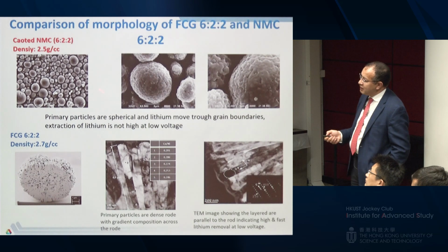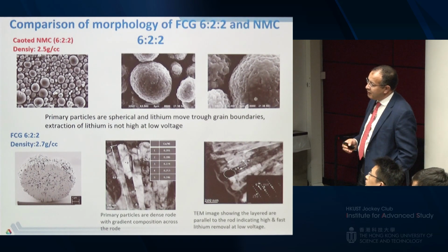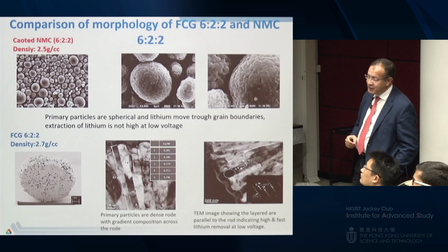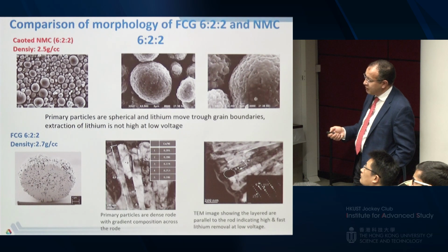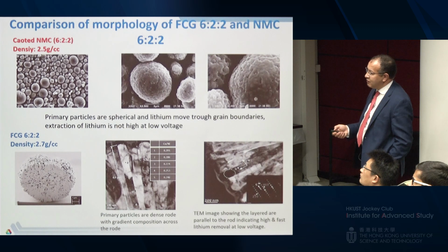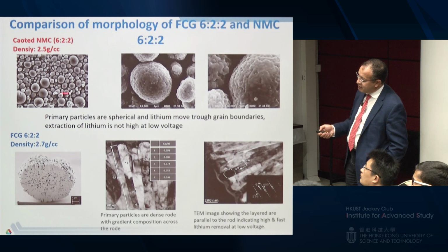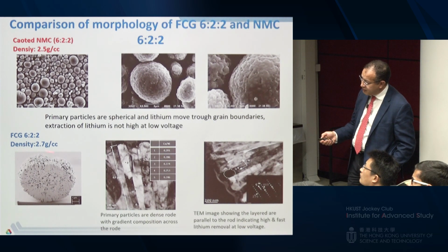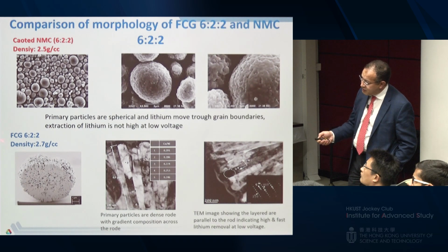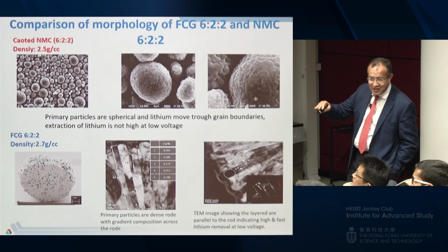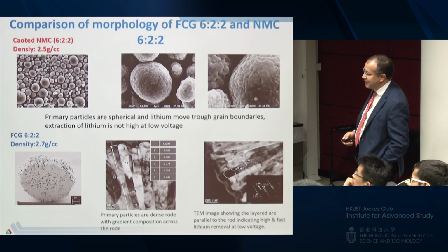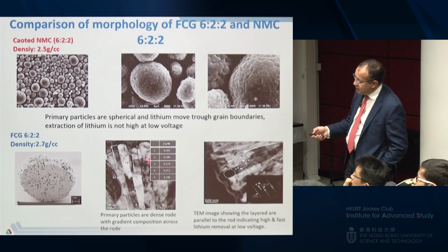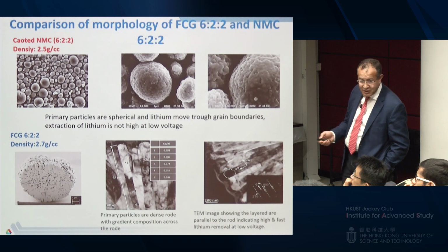Here is the comparison between the existing technology that is in electric vehicles now, like in BMW or the Chevy Bolt from GM. They use the 622 nickel manganese cobalt, with 60% nickel. They are both made by co-precipitation now. This one is spherical in both cases, but if you look at the primary particle, in this case they are spherical and small, where lithium will go through the grain boundaries. In this case, we have rods, so it's very different, but dense rods. That's the reason why the density is higher. This is the same average composition, because the composition here is changing from the core going to the surface. Remember that. But the reason why we have high density is because of this structure. It's totally different from here. Now, density means energy.